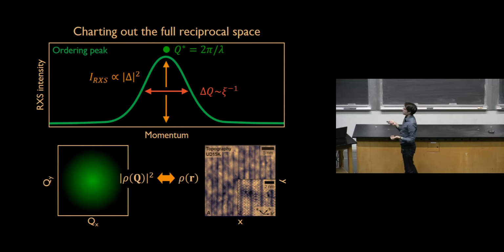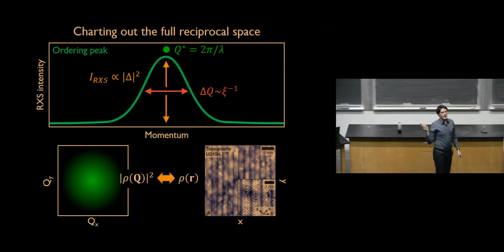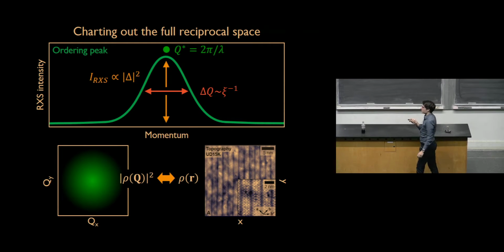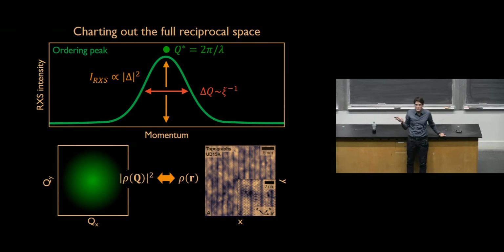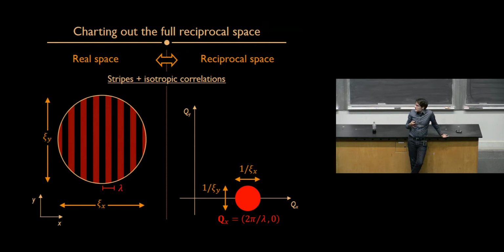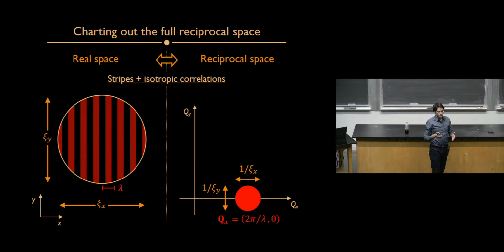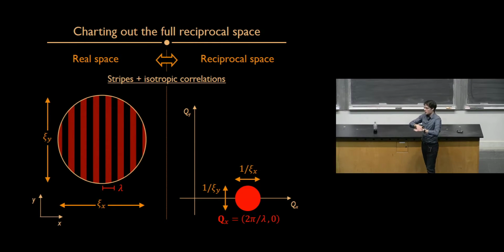Ultimately, this full information that's available in reciprocal space is closely connected to the real space structure of these ordered states, because what we measure in reciprocal space is nothing but the power spectrum of the Fourier transform of this electronic density in reciprocal space. So let's now talk about the, let's say, two-dimensional structure of charge order. And one thing we know is that charge order is really two-dimensional, so there is no coherence along the out-of-plane direction. So we can say that in a way, the only two variables that matter in reciprocal space are the ones that are parallel to the copper-oxygen planes, because charge order is really a two-dimensional phenomenon for the copper-oxygen planes.